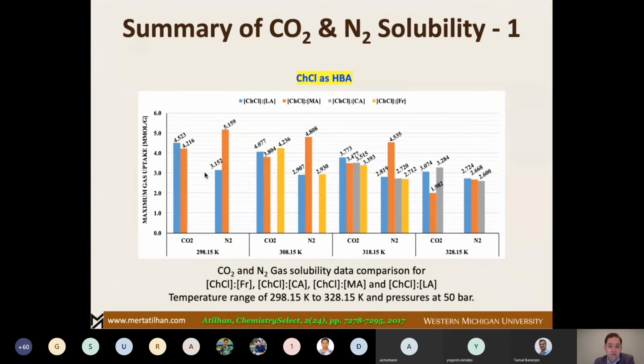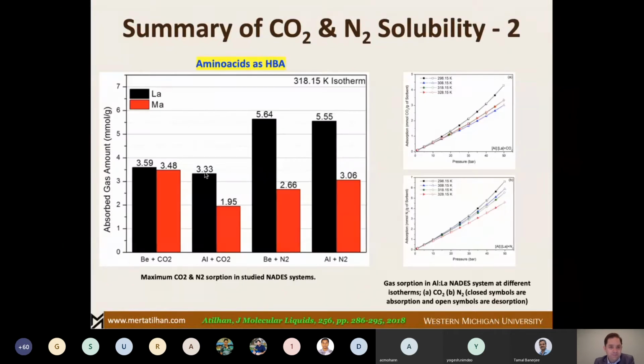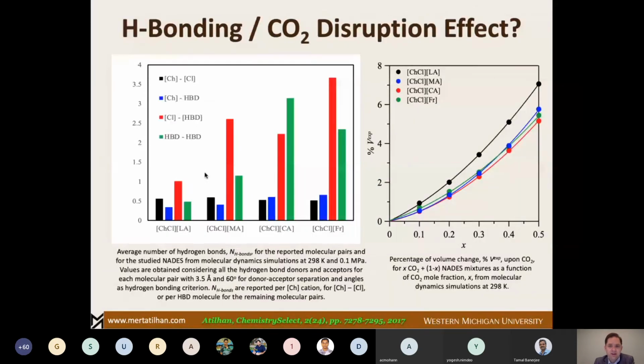But interestingly, I wasn't expecting to see that in several cases, nitrogen is giving higher solubility. So that was interesting. And for the amino acid systems, it was the same. So nitrogen solubility was higher than the CO2 solubility. So this obviously has an effect on the selectivities.